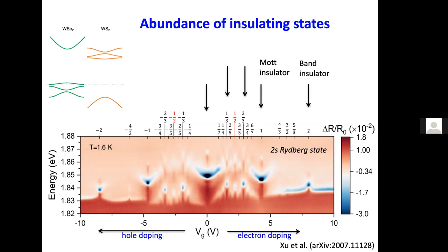So I probably didn't answer this very clearly. What we are seeing is the exciton response from the sensor layer, and what we are doing is trying to increase the doping density in the sample layer. When the sample layer is neutral, you see this feature. Then when you increase the doping density in the sample - you can think of it as a 2D electron gas in the sample - that will dress the exciton in your sensor, and this is part of the signature of that dressed exciton in the sensor layer.